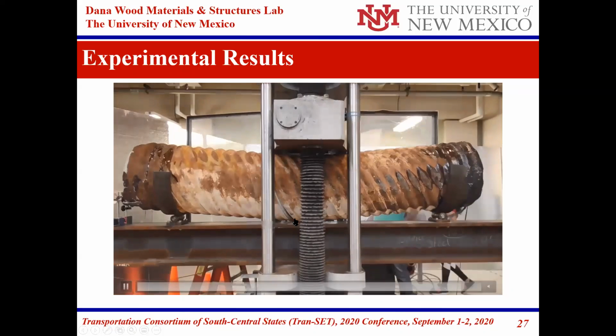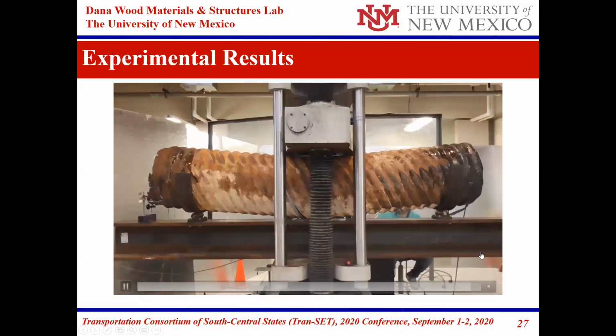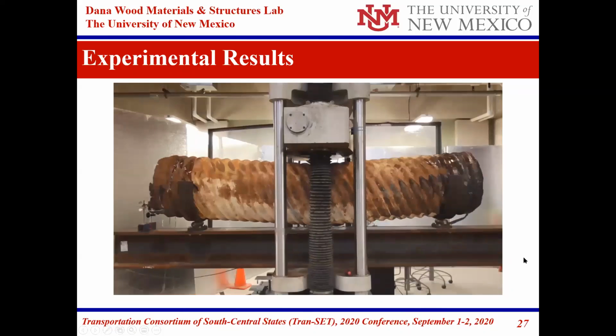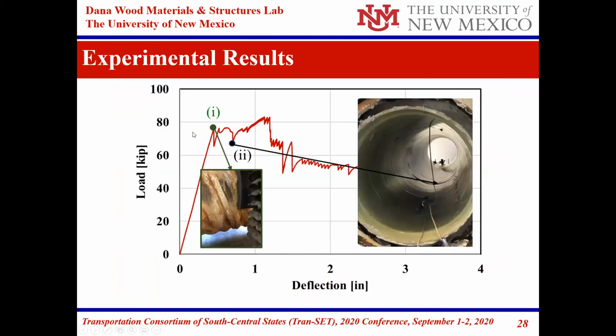But you can see here the bigger failure happening because of the seamless joint, because of corrosion opening. The capacity, again, similar at 76 kip, failures happening inside the GFRP. But the main difference is that there's still a lot of capacity here, but there is a considerable loss of capacity in the case of corroded pipe because of the seamless joint.